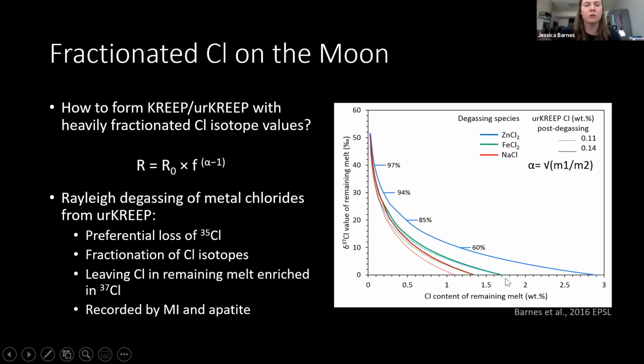And so when you compute the loss of chlorine from melts that have a range of chlorine contents, we can see that as we lose chlorine species like zinc chloride or iron chloride or even sodium chloride from lunar melts, it's an easy way to fractionate chlorine isotopes. So with progressive loss, you're preferentially losing the lighter isotope over the heavier isotope. So what you're doing over progressive degassing is you're losing chlorine 35 relative to chlorine 37. So any residual liquid remaining after, say, 97% of degassing is going to be enriched in chlorine 37, and you'll have a higher delta chlorine 37 value. And that's what's being recorded by apatites and melt inclusions.